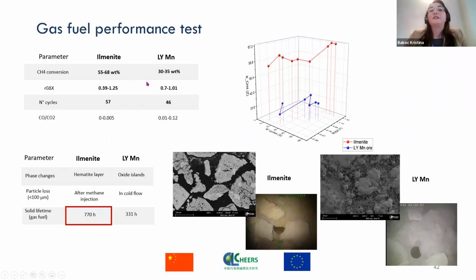For the values of oxygen transfer capacities, or R0 delta X, in both cases, we see that we reach satisfying values. However, the time to reach it is not the same. So ilmenite requires a higher activation period than is the case for LYMN, because they already start with significantly higher values for R0 delta X of 0.7 with respect to approximately 0.4 in the case of ilmenite. Finally, if we take a look at the ratios of CO to CO2 at the fuel reactor outlet, the more performing material seems to be ilmenite, as it is way lower in the values than in the case of LYMN ore.